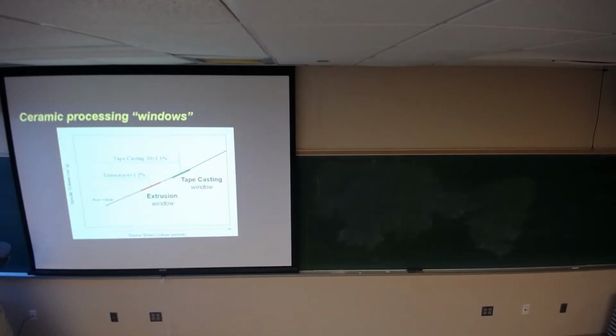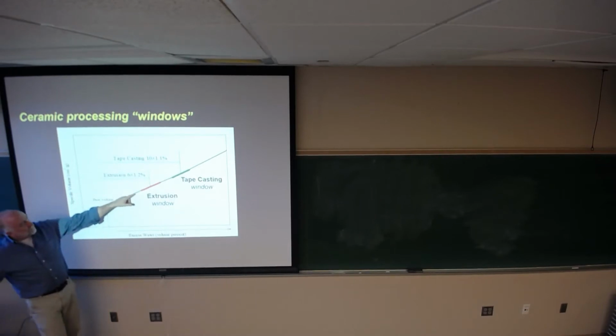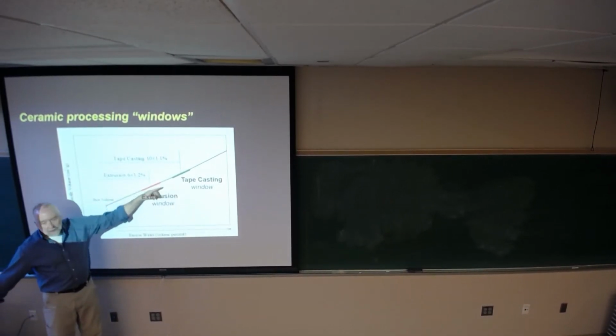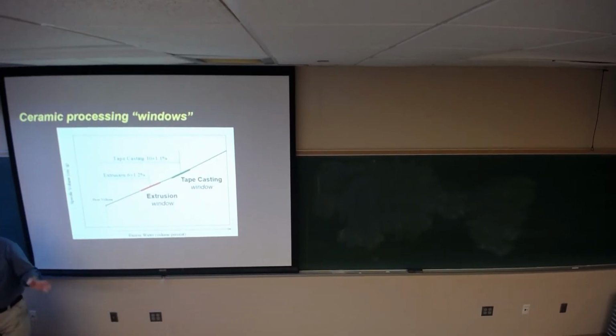If I'm sitting at, say, 4% excess, and I add 1%, I jump to 8, I can miss my window altogether for extrusion. And if I'm in zirconia, it's worse, because I have a density of 5 or 5.6. Now one weight percent is 5 volume percent. I can blow right past the window.